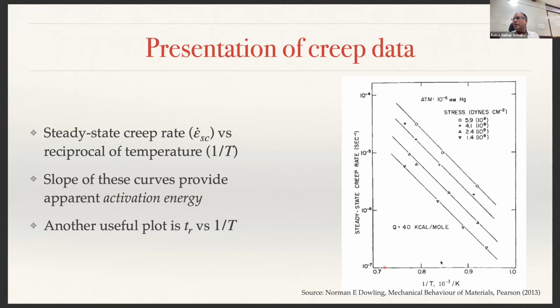Steady state creep rate, as a function of 1 over T, gives you a slope, and then you see that the slope of this line is constant, and the slope gives you activation energy Q, in kilocalories per mole. And this activation energy tells you the amount of energy barrier that you need to cross in order to go from transient creep to steady state creep.